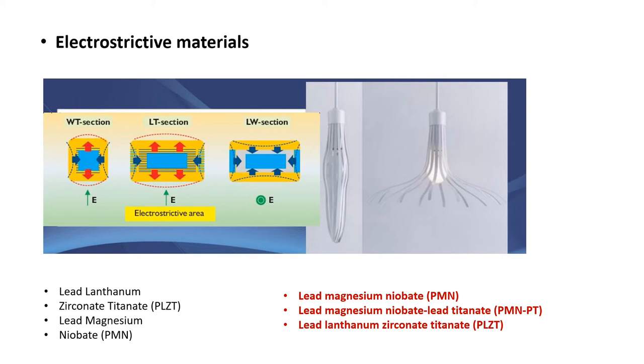Although all dielectrics exhibit some electrostriction, certain engineered ceramics known as relaxor ferroelectrics have extraordinarily high electrostrictive constants. The most commonly used are lead magnesium niobate, lead magnesium niobate lead titanate, and lead lanthanum zirconate titanate.